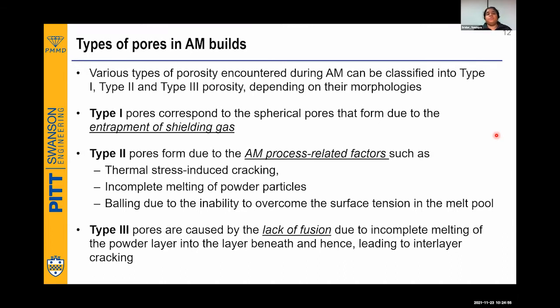But type 2 is the most serious pore which you can have in an additively manufactured build part. They are formed due to AM process related factors. For example, thermal stress induced cracking, incomplete melting of powders, and the third one, the most important one, I think many might have known, is called balling. In balling, you can see literally a ball kind of feature standing over the melt pool, because it is not able to overcome the surface tension in the melt pool.